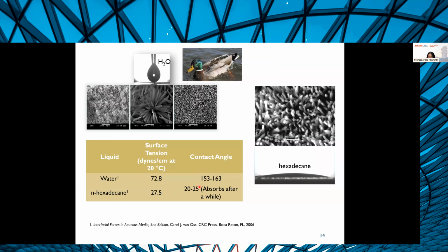It was 20 to 25, but we have a porous material. So to add insult to injury, not only did it have a low contact angle, it even absorbed the hexadecane after a while. So we were really disappointed about this. And, you know, chemically speaking, we had already brought out the big guns in terms of functionalizing this material because we've already fluorinated it. And so we can't really lower the surface energies any further, at least in our minds. So we thought, how do we actually repel hexadecane? There must be a way to do it. And we're pretty stubborn, so we thought, let's think about this a little bit.